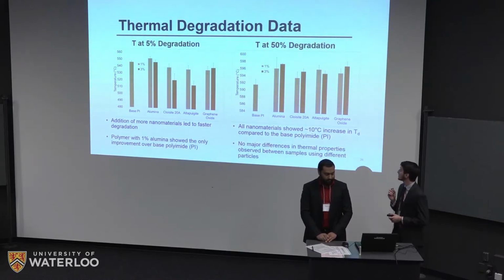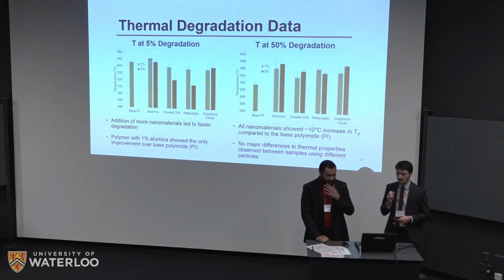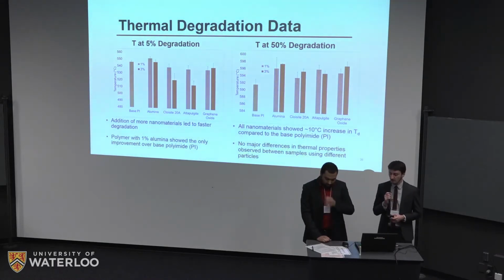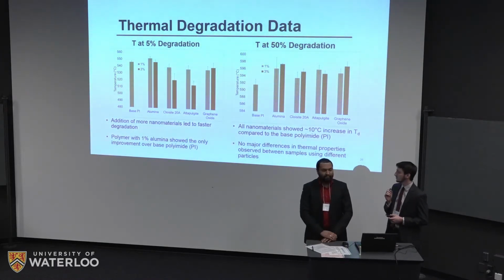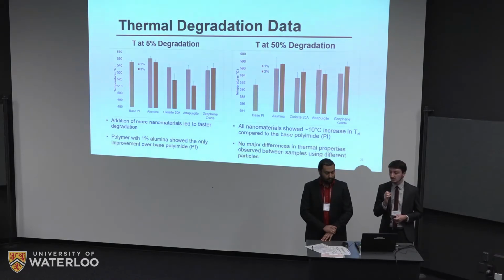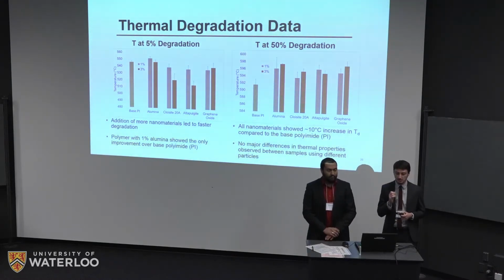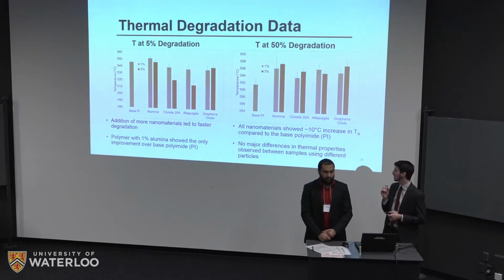However, when we look at the 50% degradation temperature, which is kind of more indicative of when the peak degradation rate is occurring, we notice that we were able to improve the degradation temperature at that point by up to like 10 degrees Celsius, particularly for the alumina sample. This is definitely our best nanomaterial because it showed some improvement in both the 5% and 50% degradation.